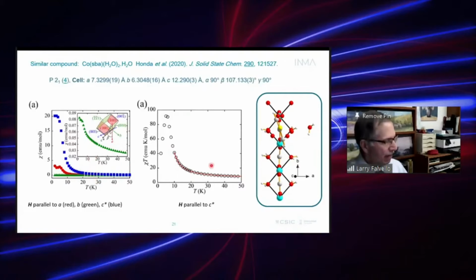And C star happens to be the direction perpendicular to the plane of this chain, sorry, the chain would not have a plane, a chain is one direction, but the plane through this ribbon is perpendicular to C star. So if the magnetic field is there, they see this response here in blue. Okay. So that raises the question, do we gain anything by measuring single crystal susceptibilities?